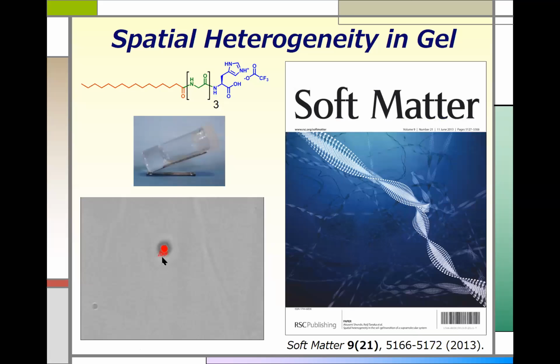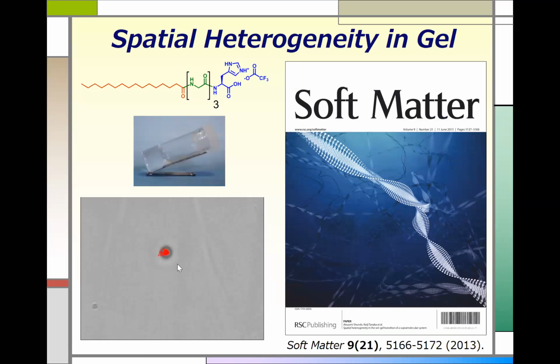And see here, we put a tiny particle. The size of this particle is about, let's say, 100 nanometers. Then we are able to extract their physical properties, like electrical properties. I mean, viscosity around here. I mean, this is kind of a local viscosity. But the resolution of that technique is, as I told you, less than 1 micrometer. We are going to smaller and smaller.